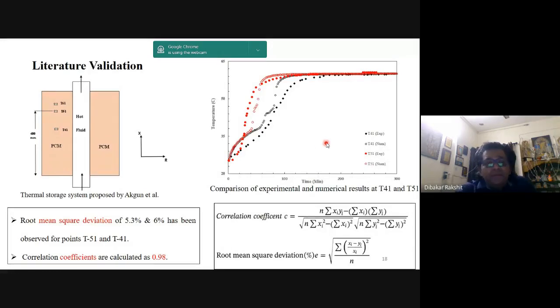So after getting a proper match between the experimental and the numerical results, we then started plotting the temperature versus time for all the temperature sensing locations individually, and you will see that after a certain point it reaches an asymptotic limit. Of course, it is after that point that it is storing or releasing energy in terms of latent heat, working as a latent heat thermal energy storage medium. It is not during this gradient, and this is the time after which it reaches the asymptotic limit.